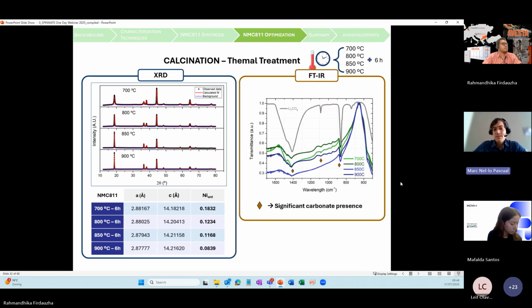For the Fourier transform IR, we observed that for all the samples, there were absorbance peaks that I have marked in the figure that indicate there's a high quantity of carbonate. There's a significant presence of this on the samples, and that correlates with the fact that we are synthesizing them in an air atmosphere. So it's very likely for this kind of reaction to happen between lithium, nickel, and the carbonates in this atmosphere. So for the next step, the idea was to remove all these surface impurities and also try to improve the nickel cation mixing. And to do so, we assessed the calcination atmosphere of the sample.